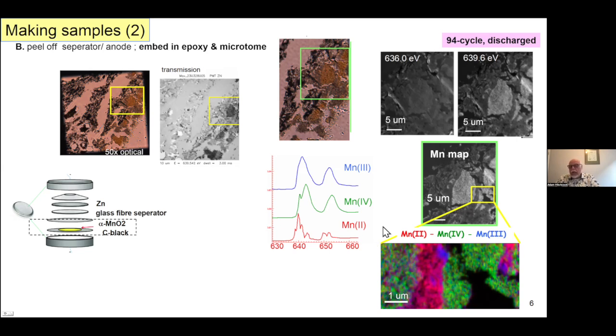This is a color-coded composite of the maps that were derived from that full manganese 2p stack, such that we can tag each pixel as either pure manganese 4, original material, or the manganese 2 material, which is highly degraded, and then there's still small amounts of this manganese 3. This was actually up here, the 94 cycles. So typically by 50 cycles, they're pretty useless as batteries. So this was a fully degraded cell that was not making very much difference between charge and discharge in terms of its potential. And it was left in the discharge state. So that's consistent with the chemistry going from the intercalation driving conversions from manganese 4 to manganese 3 and back to something where the manganese is no longer in a state where it can actively participate.